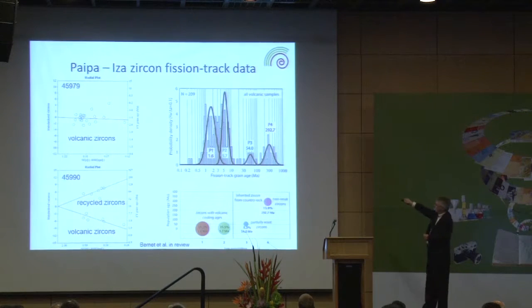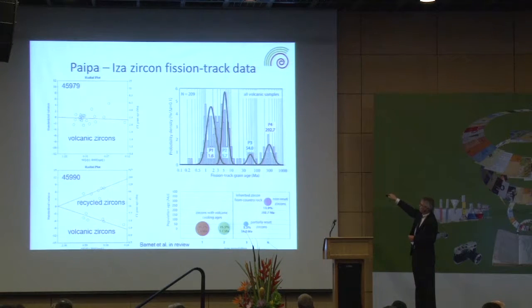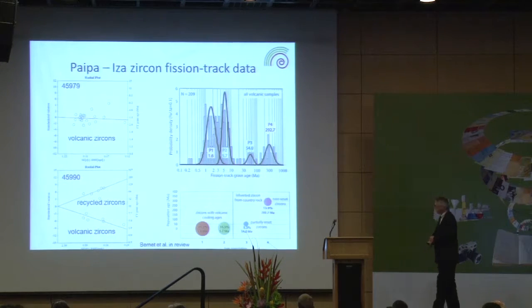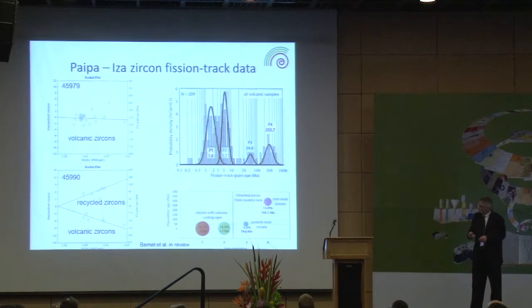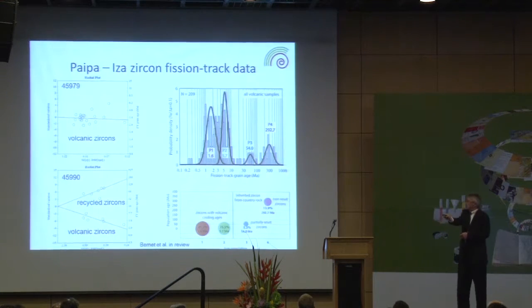Right? And if you look at the proportion of these peaks, we can see that about 80% of the zircons that we've analyzed fall into these young peaks that we associate with the volcanic activity, and then the other ones come from the recycling. So here is about 5% of the grains that we consider as being partially reset, and then about 14% that have not been reset at all, or maybe only very little.